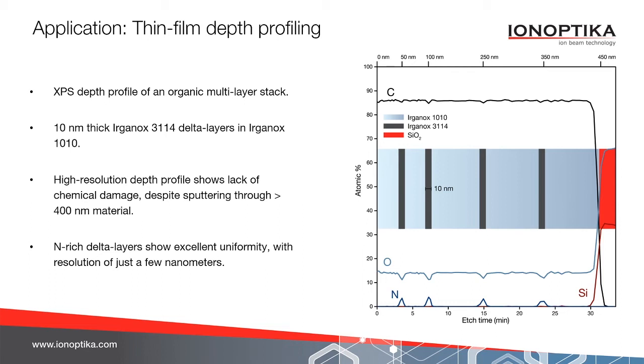So to go into the applications for the GCIB, they fall under a couple of categories. One is depth profiling. So for XPS particularly, the GCIB 10S is an incredibly powerful tool to obtain very, very high resolution depth profiles, particularly when looking at soft materials, for example, polymers or organic materials. Here we show a multi-layer stack of Irganox 1010 interspersed with very thin layers of Irganox 3114. Now the Irganox 3114 layers are only 10 nanometers thick within a film that is approximately 450 nanometers thickness total.